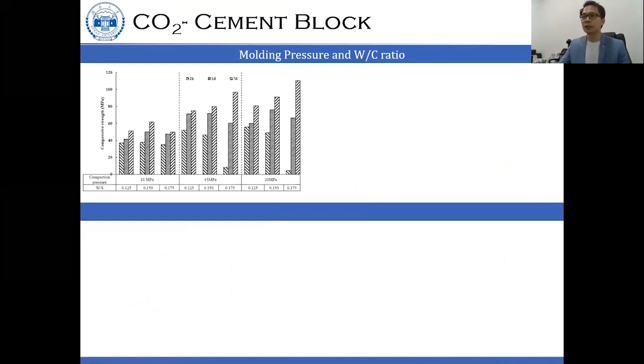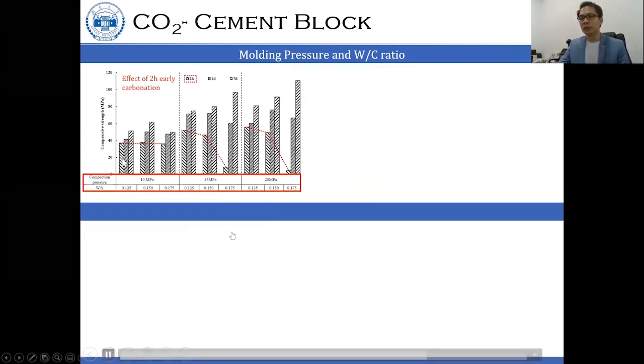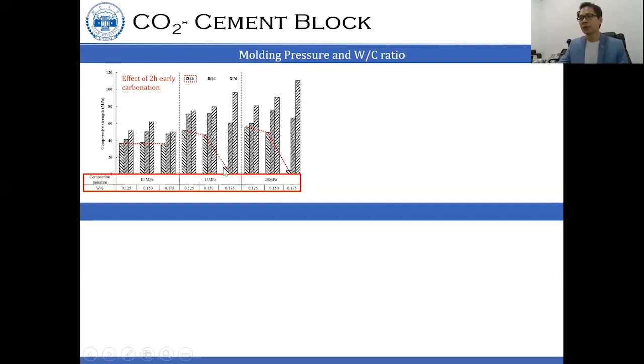So as for the CO2 cement block, we also have investigated the compaction pressure and water to solid ratio. And this is also without preconditioning. We have tested the effect of 2-hour early carbonation for different samples. So 2-hour carbonation refers to the first column. We can see there is no effect under the low molding pressure if we change the water to solid ratio. However, as for the high molding pressure, if we increase the water to solid ratio, there is a decreasing trend for the strength, especially when we reach the high water to solid ratio of 0.175.